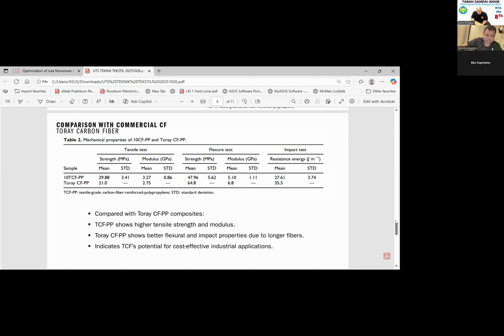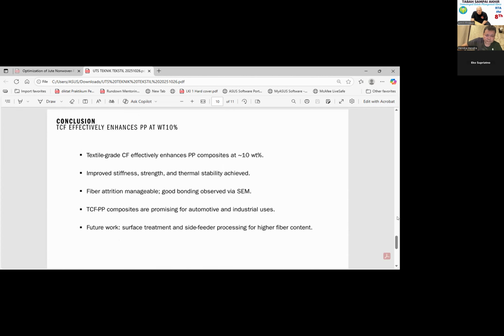So last but not least, let's conclude this presentation. Nadia, can you go to the next slide? Let's wrap up with the conclusion. This research showed that textile grade carbon fiber can effectively reinforce polypropylene composite, providing substantial improvement in both mechanical and thermal properties. The best performance was achieved at around 10 weight percent of fiber loading, where the composite demonstrated the highest tensile and flexural test results, good fiber dispersion, and stable thermal behavior.